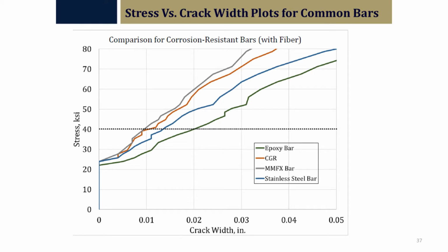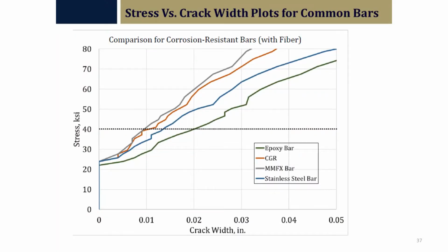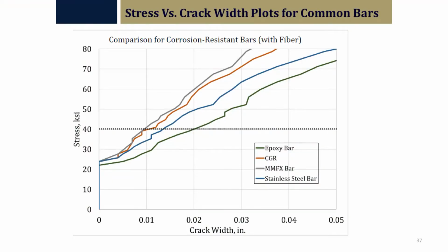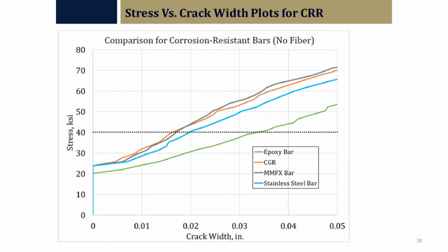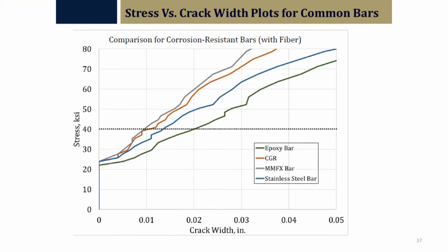Test results. This little black dotted line is just a data point where they took 40 KSI and they said, we're going to put the data points on there and say this is where the numbers lie. It's not a huge significant number, but it's just a data point that they set out in there. Again, MMFX and continuous galv separating from stainless and epoxy, but all upper left and higher than the epoxy. And this one was with fiber, corrosion resistant bars with fiber, and this one was without fiber. So again, a pretty significant difference between the two with fiber and without fiber. Pretty similar results. So this one, particularly the grouping's a little closer with the continuous stainless MMFX.